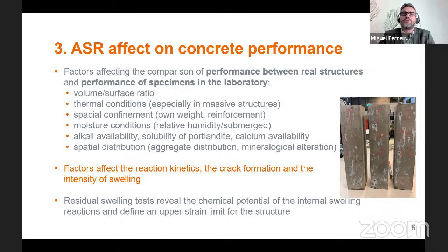reactive aggregates, etc. So if we compare these two distinct situations, a lab sample and an in situ structure, they vary greatly. And these differences, these factors, are what create different reaction kinetics from the lab to the real structure, and they affect the crack formation and the intensity of the swelling. So this is the challenge for us at the moment: how to take the results from what we get in the lab and extrapolate that to performance in the structure and try to start answering some of the questions of the owners. So this is one of the aspects that needs to be looked into further.